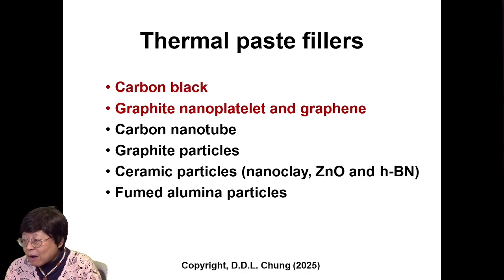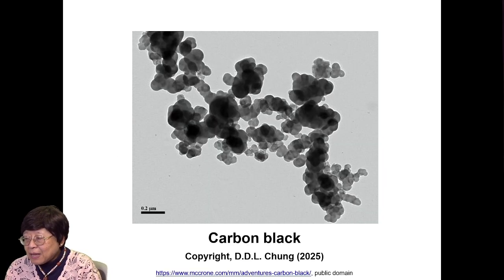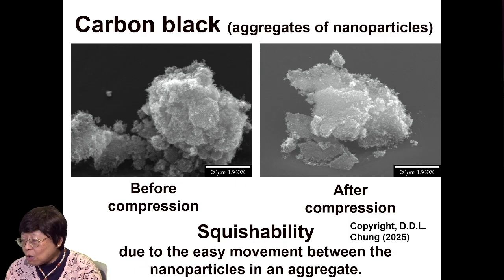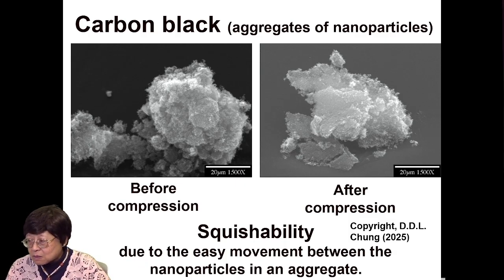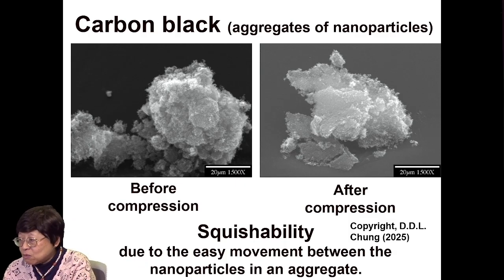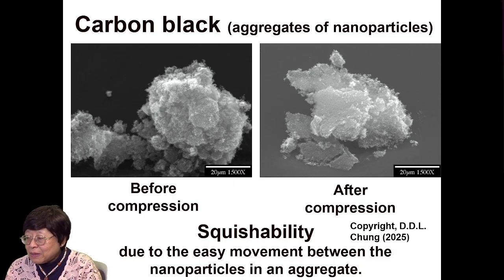Now, carbon black and graphite nanoplatelet and graphene, let's talk about these first. Carbon black, as I said, has a nanostructure in which you have nanoparticles making aggregates. And these nanoparticles are just connected by van der Waals forces. So it's very easy to squish down the aggregates. Shown at the left is before the squishing. The right is after the squishing, and you can see the squishing. It's due to the easy movement between the nanoparticles in an aggregate.